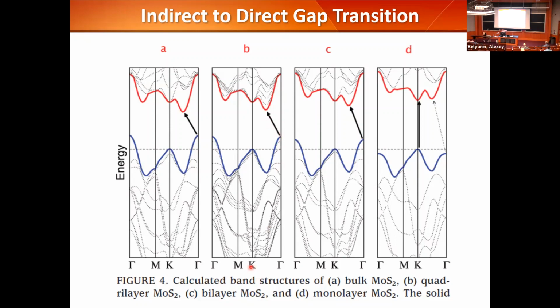K is the edge of the Brillouin zone. As you can see, this is a bulk, 4-layer, 2-layer, monolayer. Only in the monolayer limit, the bottom of the conduction band and the top of the valence band now align, becoming a direct gap semiconductor. Even in the bilayer, the bottom of the conduction band is in the middle of the Brillouin zone, and the valence band is at the center of the Brillouin zone, so they do not align. That makes the optical absorption or emission inefficient. So this transition is very critical for the high emission property.